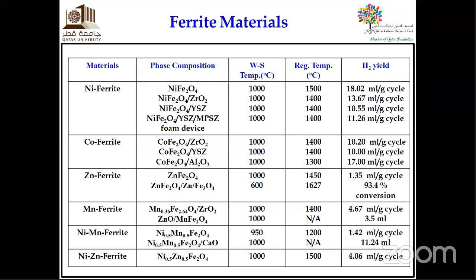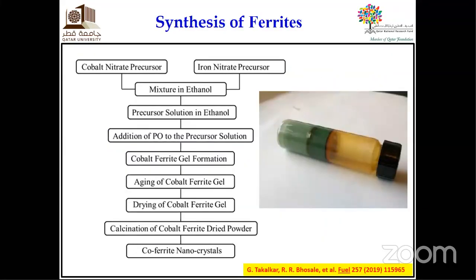If you check the numbers on the last column, which is the hydrogen yield, the nickel ferrite and cobalt ferrite seem to be more advantageous towards production of solar fuels, basically solar hydrogen, than the other metal oxides or ferrites we have used. So we decided, why not test, because this is done only for hydrogen production, but for the production of syngas, we need carbon monoxide also. So we decided to test the nickel ferrite and cobalt ferrite materials for the solar thermochemical CO2 splitting, from which we get the CO. So the first step we did is synthesis of the ferrites.